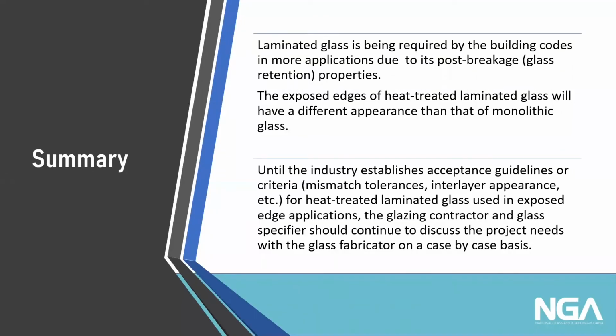So to kind of wrap up our webinar today, in summary, laminated glass is being required by the building codes now due to its post-breakage glass retention properties. The exposed edges for heat-treated laminated glass will have a different appearance, of course, than monolithic tempered glass because you have two lights that are being laminated with an inner layer, so you need to really truly watch your alignment on this. And until the industry establishes an acceptance guideline or criteria where it comes to mismatch tolerances or inner layer appearances, etc., for heat-treated laminated glass using exposed edges, the glazing contractor and glass specifier should continue to discuss the project needs with the glass fabricator on a case-by-case basis and find out what exactly is necessary.